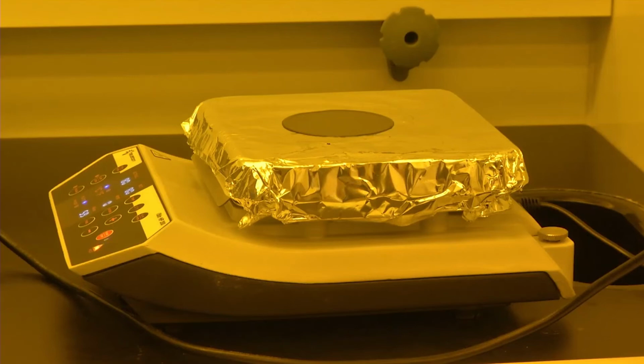Also, if we do not increase to a very high temperature immediately, there is no thermal stress built up in the polymer film, which might lead to cracking or very poor curing of the polymer. So we will cure it at 80 degrees Celsius for 1 hour and thereafter we will cure it at a higher temperature for 2 hours, which will complete the overall curing process.